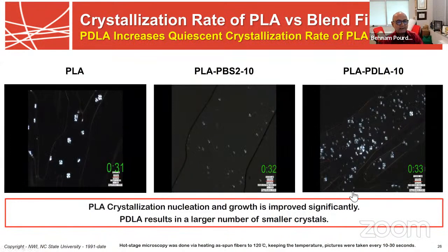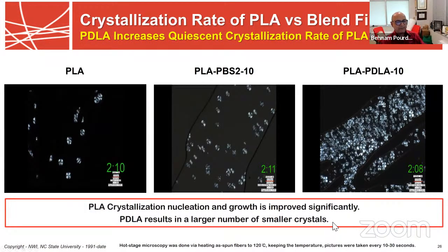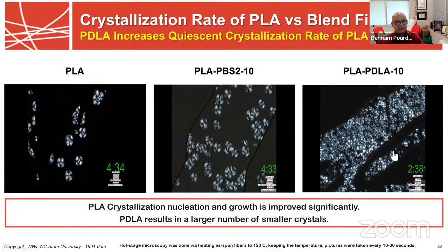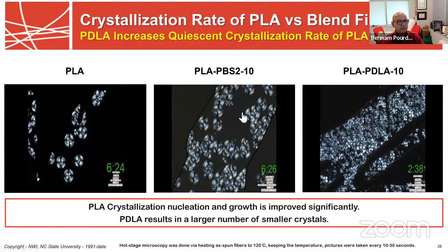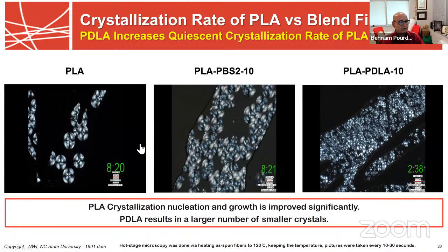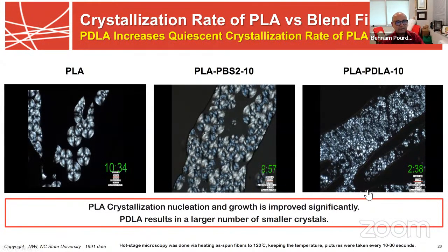Now, when you start adding additives to these, the magic happens. So if you look at the PLA, PDLA is already done. The PBS is still going, and the PLA will go forever. But of course, you also are changing the crystalline structure of these materials. So you have lots of little crystals. You have more crystals here, but larger crystals. And so these are truly acting as nucleating agents.